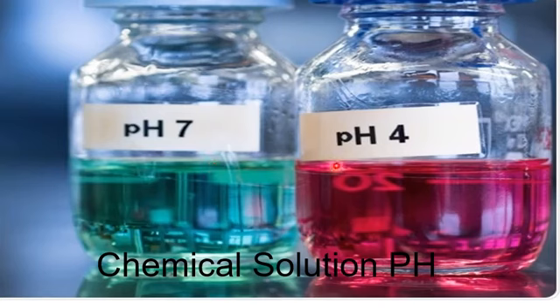So the pH value of the sol in the sol-gel process is considered in an acidic medium which is below 7, and it is usually considered below 3 in order to achieve better nanoparticles. Another aspect to consider is that with a higher pH value, like above 3, there is a possibility of agglomeration of the nanoparticles.